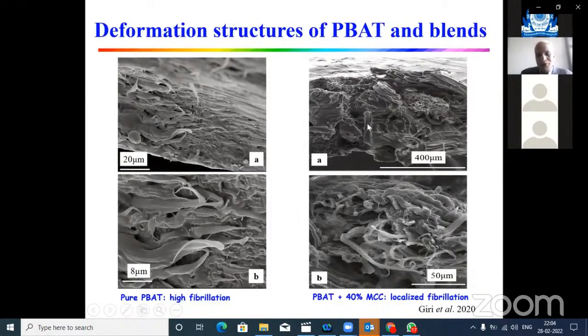So if we go to another composite, for example, with 40% by weight of microcrystalline cellulose, we see very similar structures, fibrillation, but the fibrillation is localized. For example, in the neat polymer, you have fibrillation everywhere, but in the composite, the fibrillation is only localized in some places, and in some places no. So where there is no fibrillation in the polymer, that could be the place where the cracks could be originated, and that should therefore result in much lower ductility.